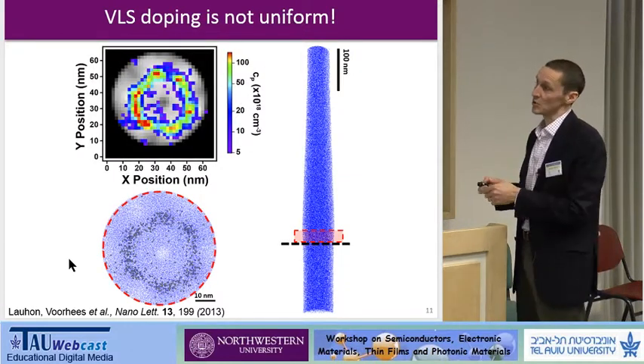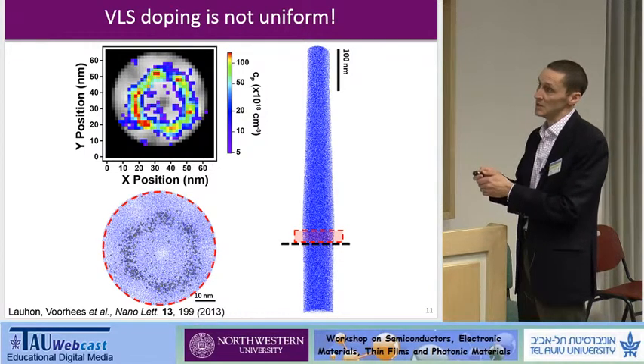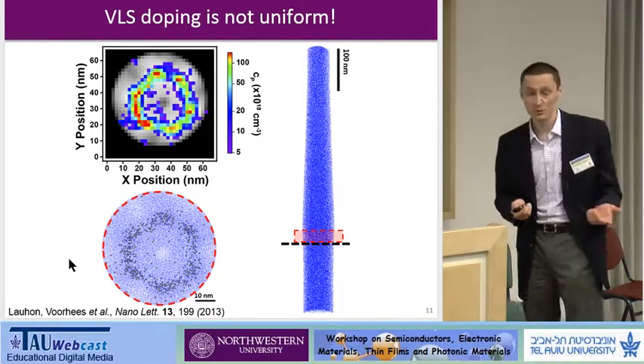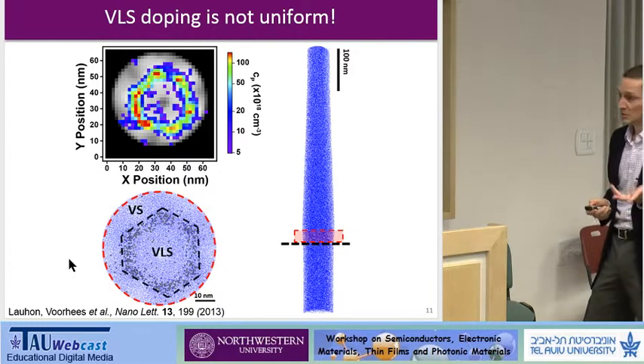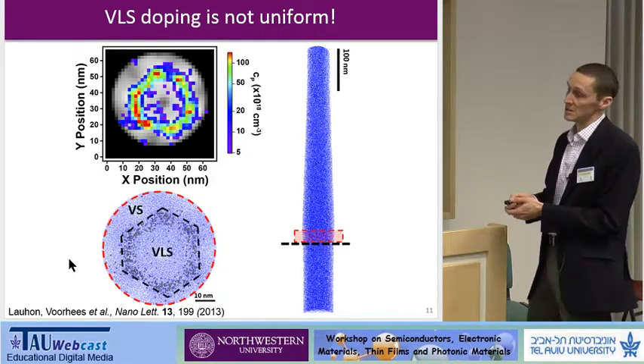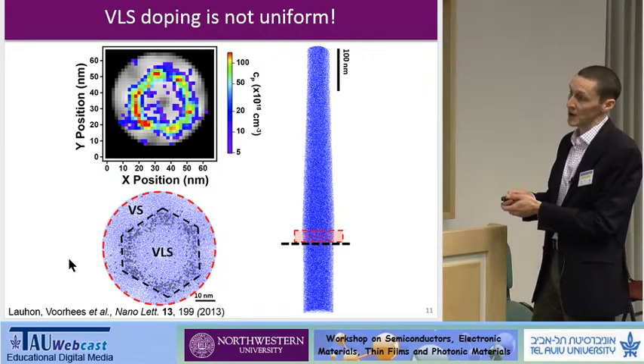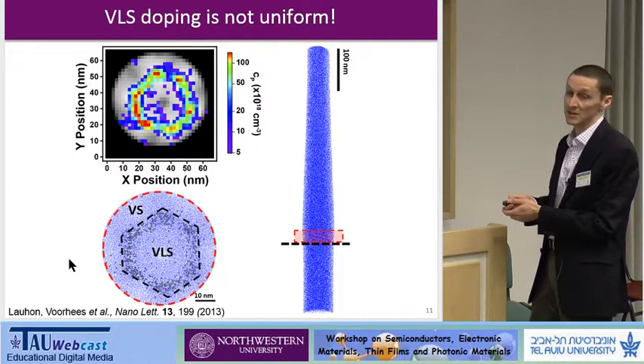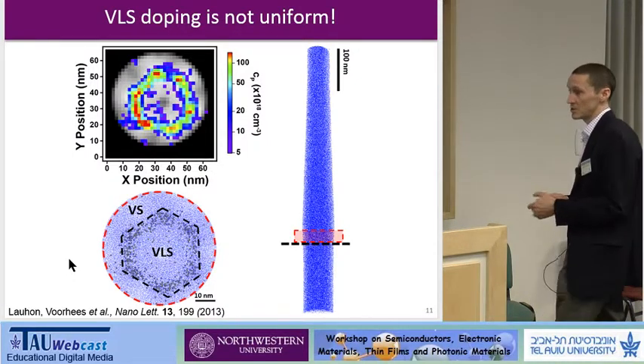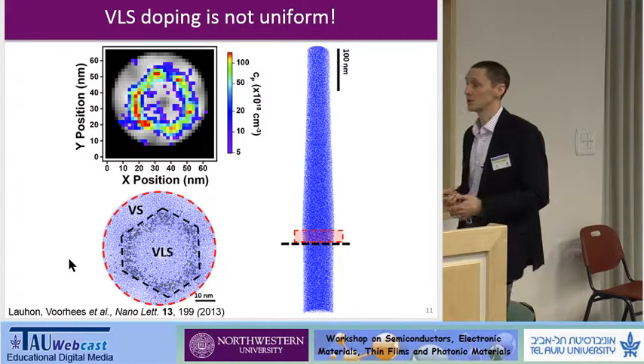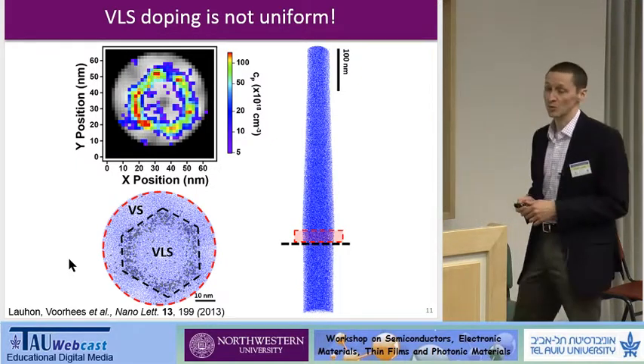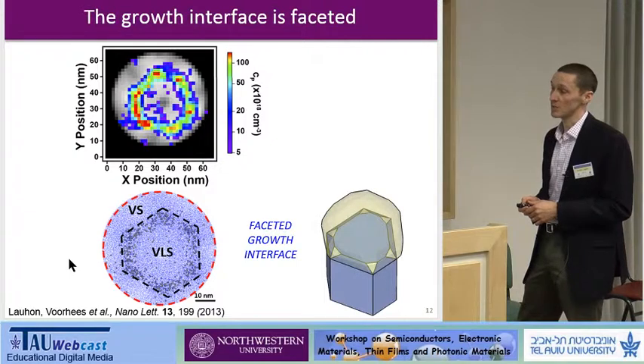And if you look at a concentration plot, there's even these distinct peaks that show up that look like they reflect the crystal symmetry. So after some time, we came to understand that indeed this doping out of the liquid was highly non-uniform. It occurred primarily at the interface. And some of that understanding came from in situ measurements in a couple other groups, as well as working with Peter Voorhees to do some modeling.